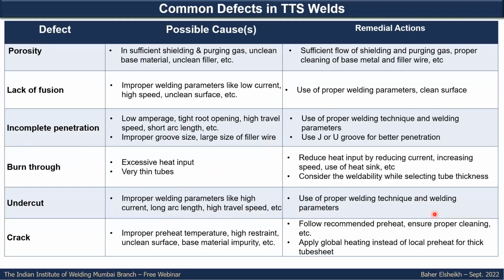You might also have cracking in the tube-to-tube sheet joint, from high restraint or an unclean surface. Here you need to think, as we said earlier, about the high heat sink you can see from the thick tube sheet. You need proper control of the heat input and heat dissipation during the application of the weld.